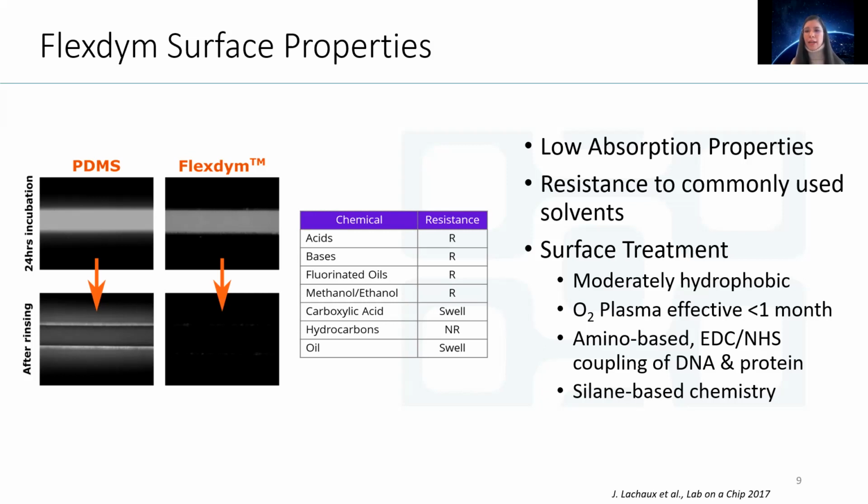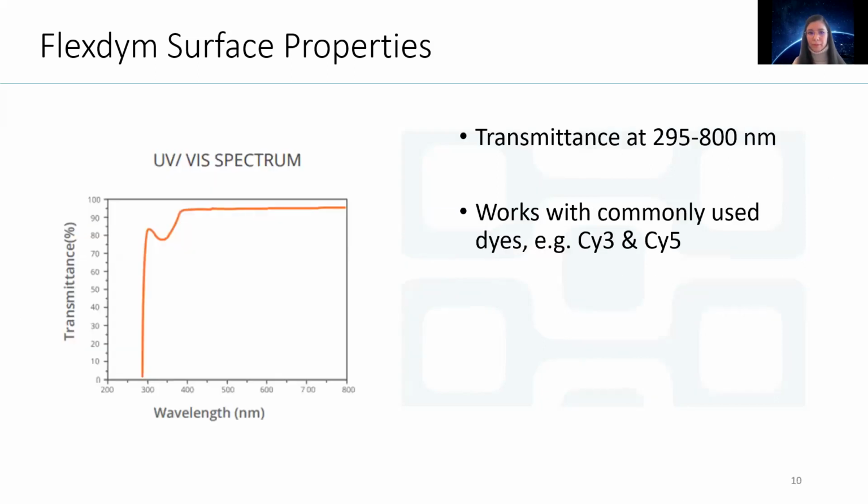And then, like many other thermoplastics, such as COC, because Flexdym possesses these ethylene components, it can be functionalized with commonly used amino-based EDC and NHS coupling for functionalization of the device with DNA and protein. And silane-based chemistry will also work as well.